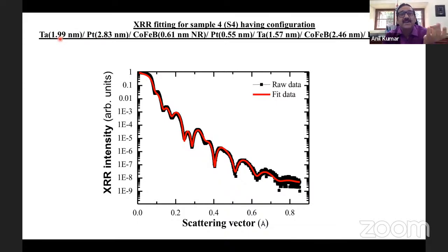Instead of that, it is 1.99. I wanted to put 3 nanometers of platinum. Instead of that, it is 2.83. I wanted to put 0.6 nanometers of cobalt and boron. It is 0.61. And I wanted to put 0.5 nanometers of platinum. It is 0.55, like that.